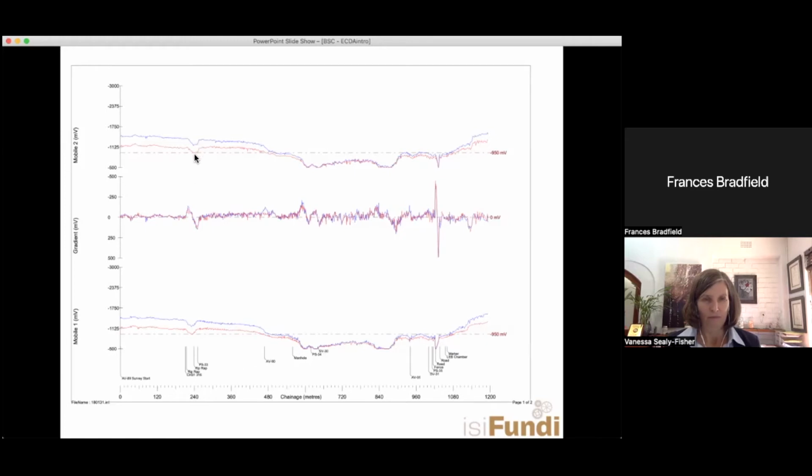And where we have our off potential, we're sitting on a borderline. So this is a defect that is not completely protected, and so we might be slightly concerned about it. It's one to put a pin in and tie up with other data that we have. It could just be that on this day we had low potentials for some reason, and at other times we usually have high potentials, in which case we'd be happy that it was protected, but we're not 100% sure.